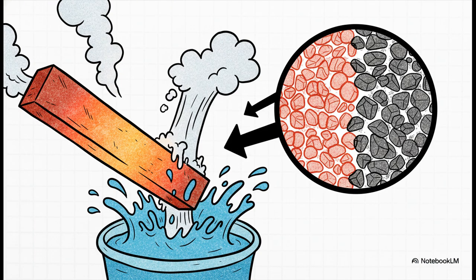Well, in simple terms, quenching is just the super rapid cooling of hot steel. But that incredible speed is the key. It traps the steel's internal crystal structure, locking it into a formation called martensite. Now, martensite is incredibly strong, but it's also highly stressed. So this speed is the secret to getting that amazing hardness. But, as you're about to see, it's also the root cause of pretty much all the problems.